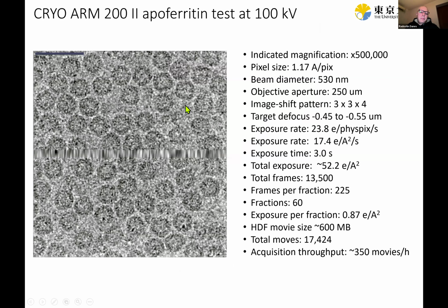So this is a sample image from the apoferritin test data sets at 100 kV. You see here we had to compromise between pixel size and number of particles. So we used 1.17 angstrom pixel. The magnification we used was very high, quite a bit above the typical magnifications used in cryo-EM, so 500,000. That's a range which typically is not used on cryo-EMs in general. So it was a bit of a challenge to operate at these high magnifications.